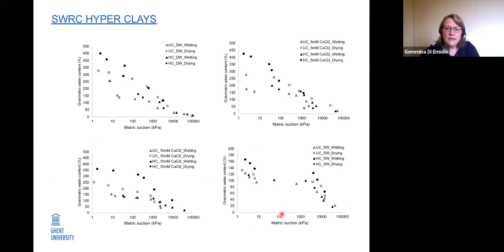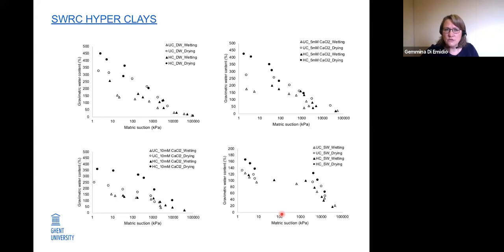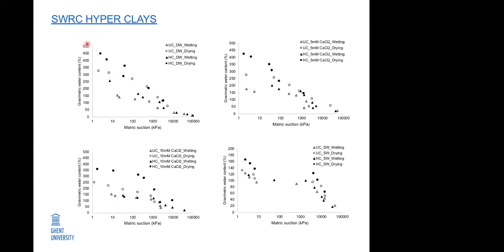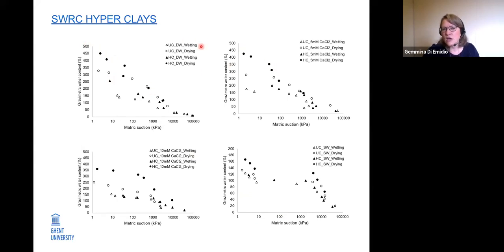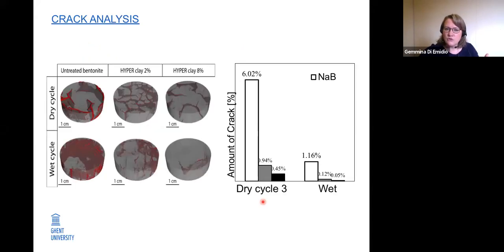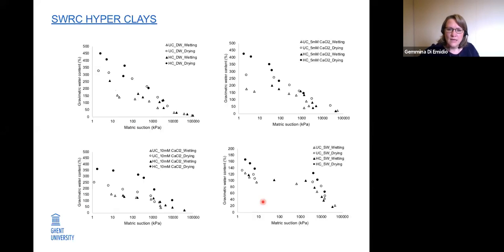Currently, my PhD student Kisar Khan is performing soil water retention curve tests on Hyperclays, as described by Professor Nasli Yesiler for GCLs. Using filter paper and humidity sensor methods, results show that Hyperclay had higher water retention capacity than untreated clay in deionized water, calcium chloride, and seawater. This suggests that the reason Hyperclay performed better under wet-and-dry aging may be due to higher water retention capacity. Further research is ongoing during Kisar Khan's stage at Bochum University using the mirror hygrometer apparatus.